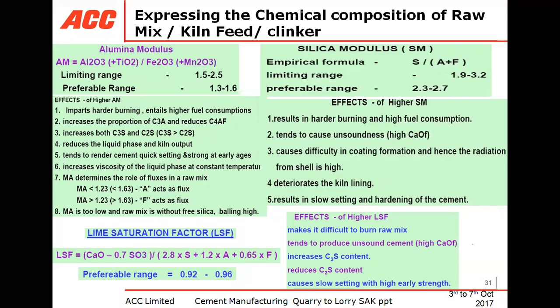We will see how it affects your cement quality. The effects of higher alumina modulus: it causes harder burning and higher fuel consumption. Secondly, it increases the proportion of tricalcium aluminate and reduces tetracalcium aluminoferrite, C4AF. You can increase both C3S and C2S to get better strength. Then it reduces liquid phase and kiln output. It tends to render the cement quick setting and strong at early ages. So alumina modulus is also very important.